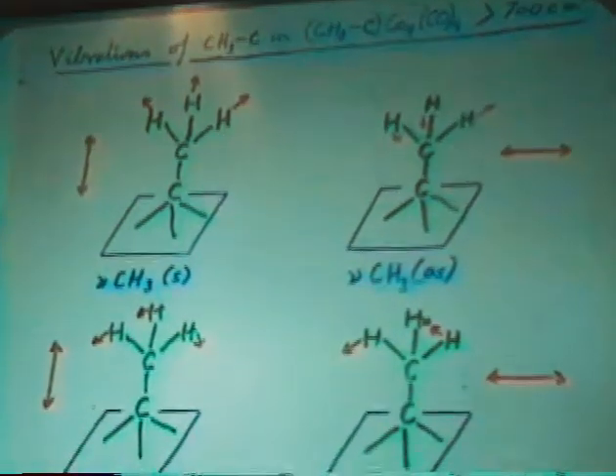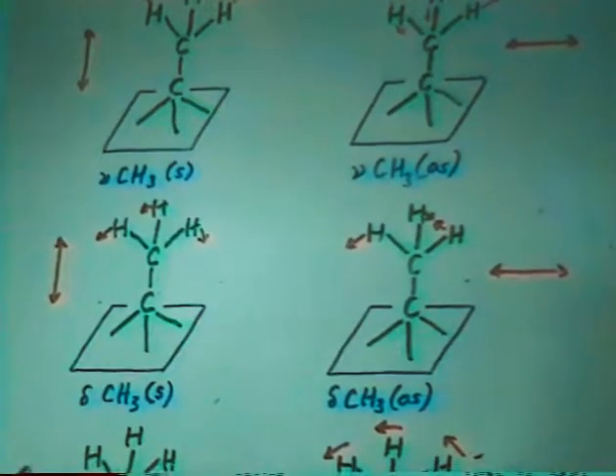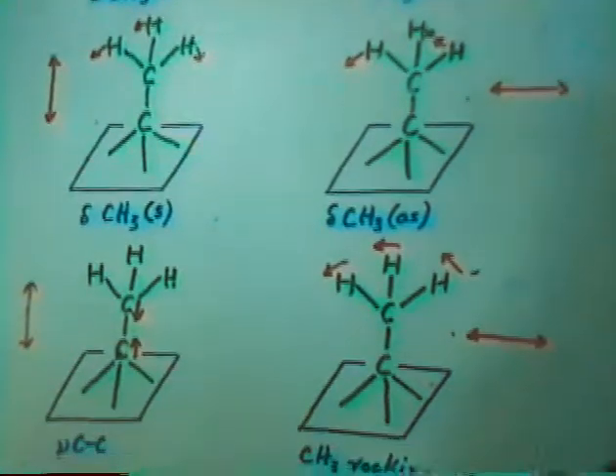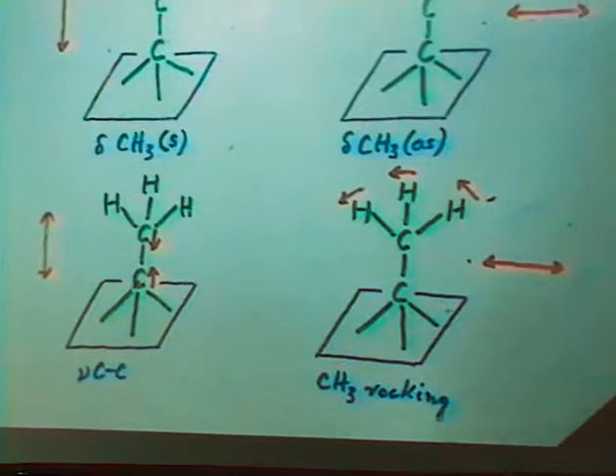Anyway, so we have this species, and of course certain of the modes have dipoles perpendicular to the surface. They should be present on platinum 111. The others should be missing, at least for specular reflection, which is the nature of the spectrum that Professor Ibach originally got. Anyway, with the help of the cluster compound, we produced a complete assignment for this species.